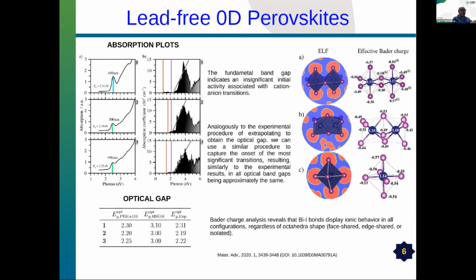The gap is small, as you can see, the band gap can be quite small here, with the vertical line. However, in figure B, the optical band gap, which matters for the absorption, is slightly larger because the density of states in that particular region has a very low number of states, which does not help to improve the absorption coefficient. And then we analyzed the effective charge to try to provide an explanation and understand the stability of those systems.